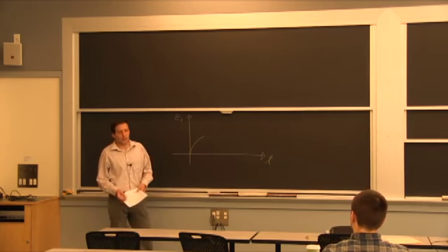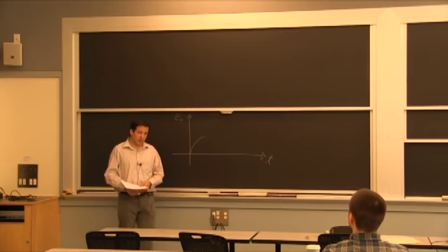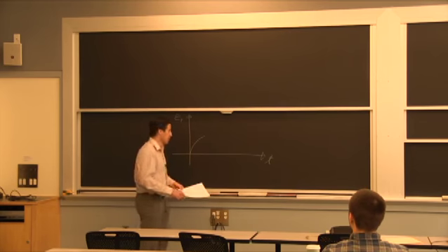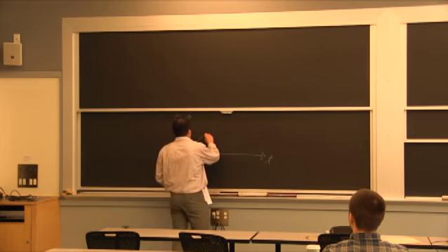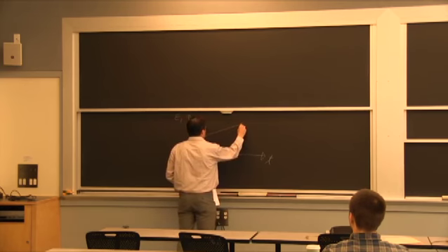So if you had a few dislocations here and there that were just about to move when you apply the load, now over time they will. But there's only so many of those sites. And that's why eventually you reach this regime of what we call secondary creep.